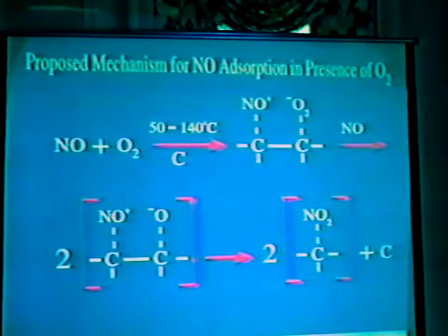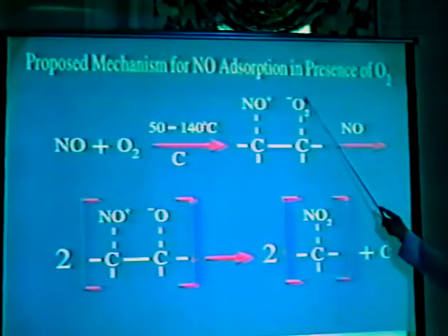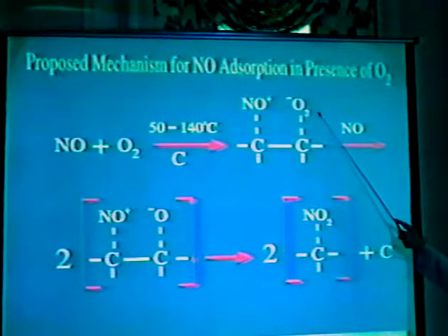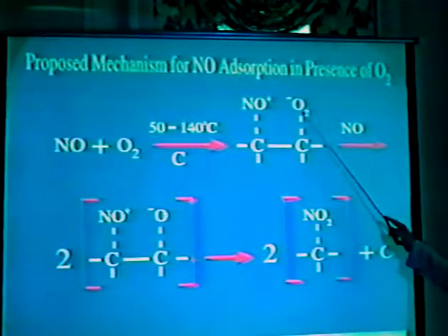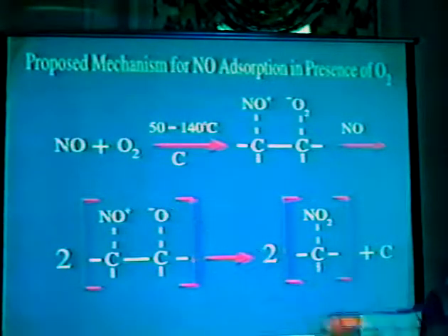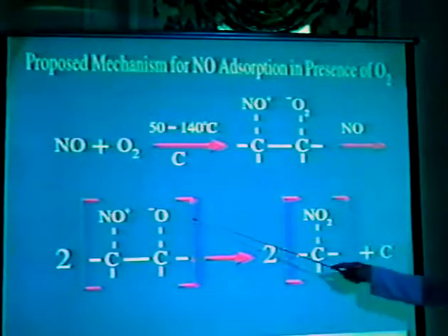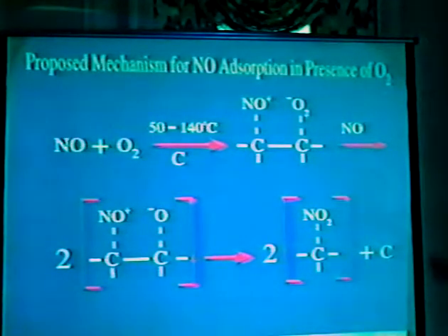Additionally, the electron affinity of both NO2 and oxygen would favor the formation of these NO2- or O2- species. Both the O2- and O- are known to exist, and therefore we would like to propose a mechanism whereby both of those negative ions are involved with the addition of more nitrogen oxide to produce NO2.